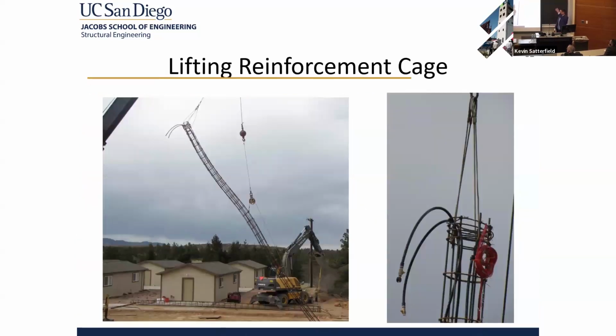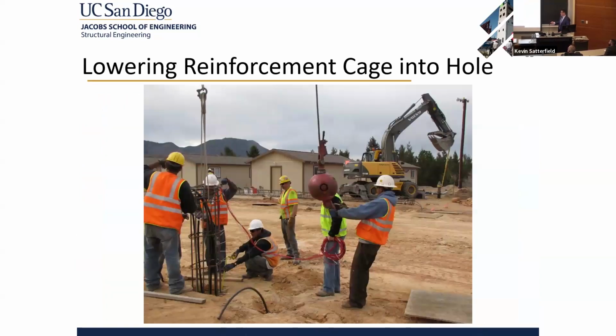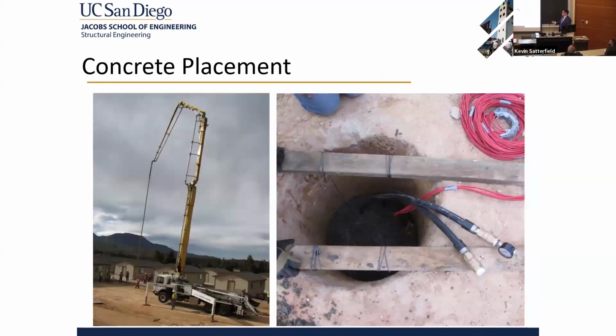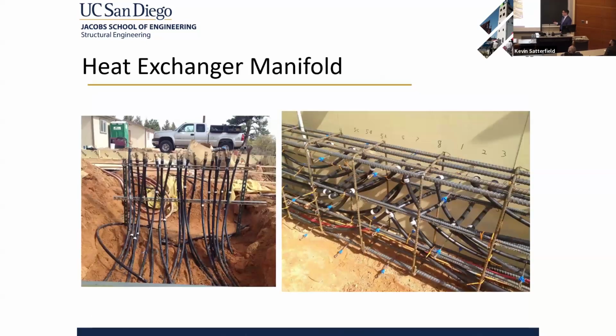Then we needed to pick these 50 feet by 2 foot reinforcement cages up. So we did that successfully without damaging any of our strain gauge sensors. And we lowered that into the hole. And you can see the dry hole here, and we tremmied concrete up from the base. You can see that they're still under pressure, which was good. We didn't have any damage. And then we brought all of the pipes into our mechanical room. This picture saved me a lot of time at one point because all of the pipes came in from different locations and they didn't come in the right order, 1 through 8. So thankfully I knew where each thing was located so I could send the water in the right location after we poured concrete into all of this.